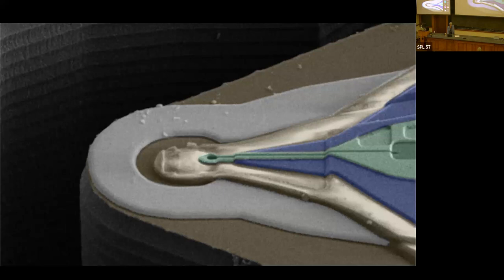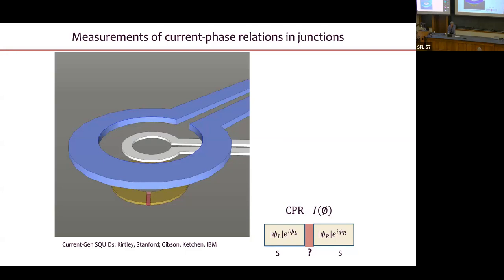So again, this is a pretty typical SQUID. Here's a pickup loop. This one's smaller than we'd probably use for current phase relations. And to apply a local magnetic field, we pass a current through this big outer loop. When I say big outer loop, in this case, it's about a micron. Okay, so now what we do is we take a ring shown here in gold and let that ring be